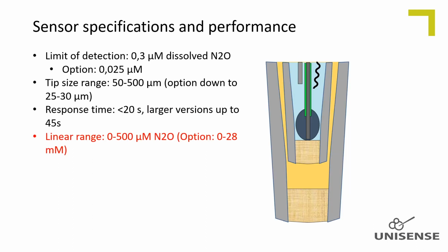The nitrous oxide sensors respond linearly to nitrous oxide concentration at the sensor tip. It will respond linearly up to quite high concentrations, but we do not recommend using standard nitrous oxide sensors in concentrations higher than 500 micromolar. Nitrous oxide is reduced to dinitrogen, which will be dissolved in the electrolyte. When measuring in high concentrations of nitrous oxide, the rate of dinitrogen production at the working electrode is high and can saturate the tip electrolyte with dinitrogen, which potentially forms a dinitrogen gas bubble. Such a bubble will disconnect the working electrode from the reference, and the sensor does not respond to nitrous oxide anymore.